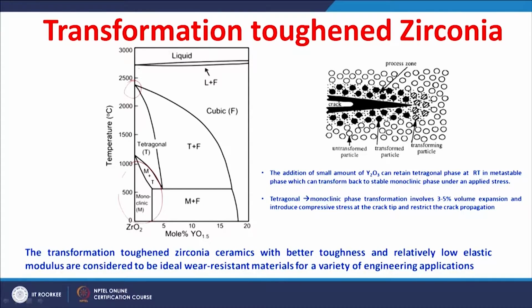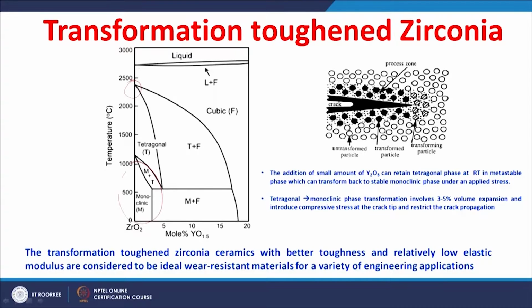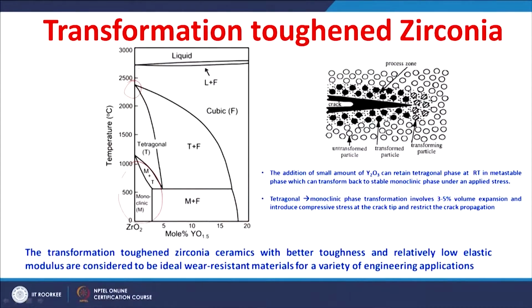So, we know the zirconia ceramic exists in three different crystalline forms: monoclinic at lower temperature up to 1170, and then it becomes tetragonal at around 2370, and then over that it is cubic before it melts to liquid. The tetragonal phase or the cubic phase can be stabilized by adding a small amount of yttria. So, addition of a small amount of yttria retains this tetragonal phase, which is metastable.